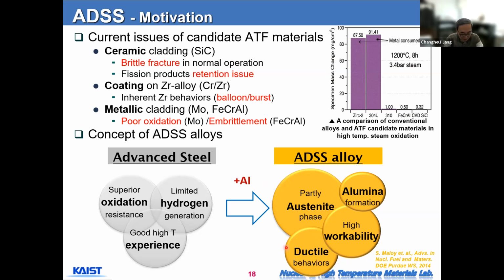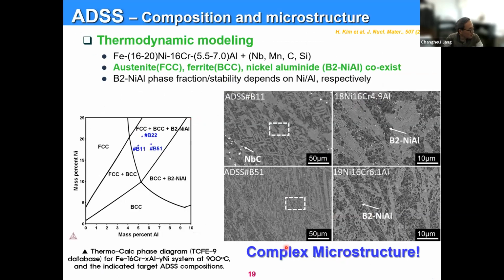Those are the features of the developed alloy called ADSS. So this one is the design scheme. We used thermodynamic modeling to arrive at a composition like this one, and this one is the microstructure after several thermomechanical processing steps. It shows a mixture of austenite and ferrite, and actually there are some small particles called the B2-NiAl phases.